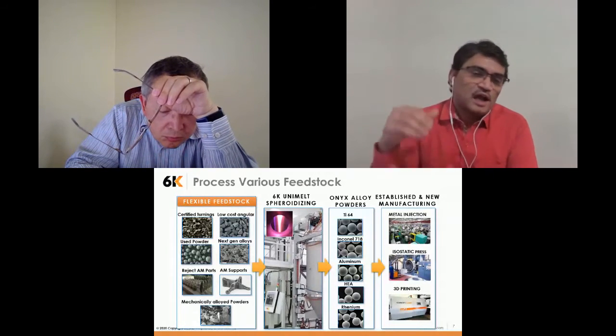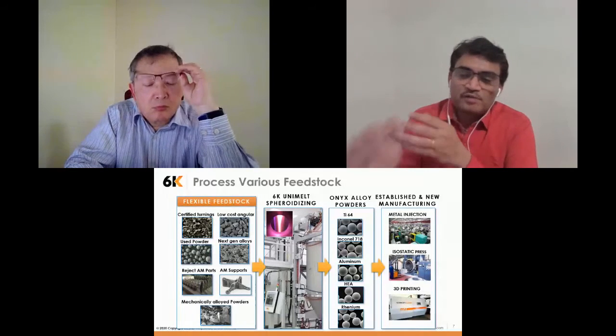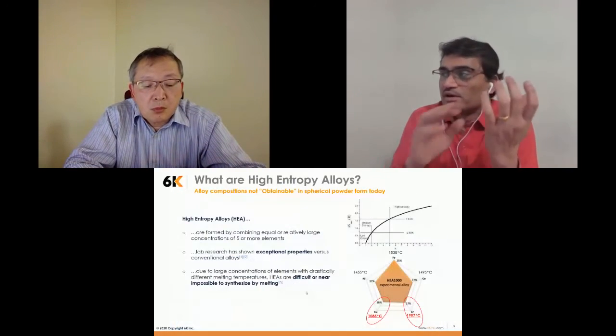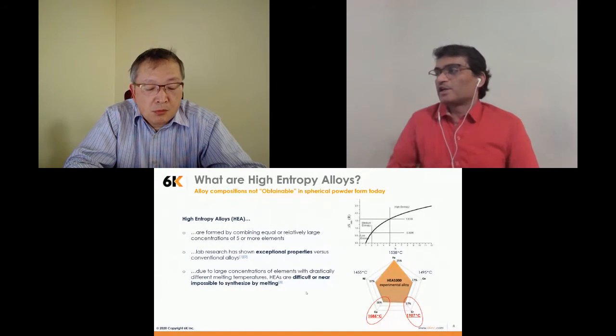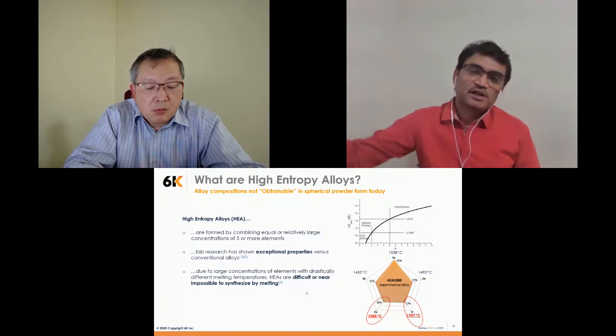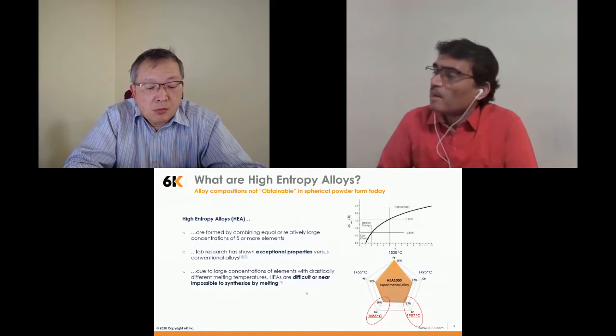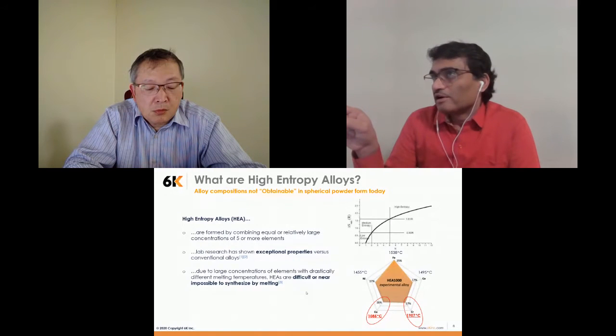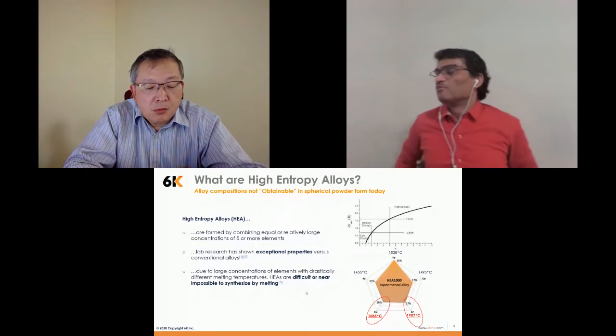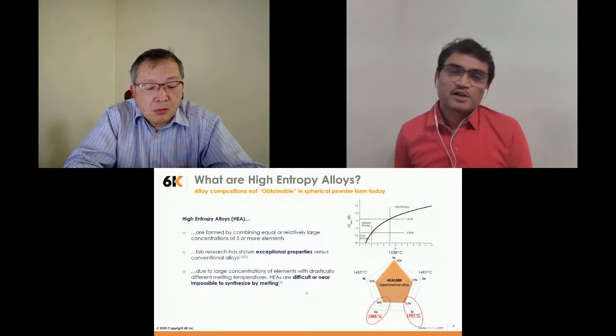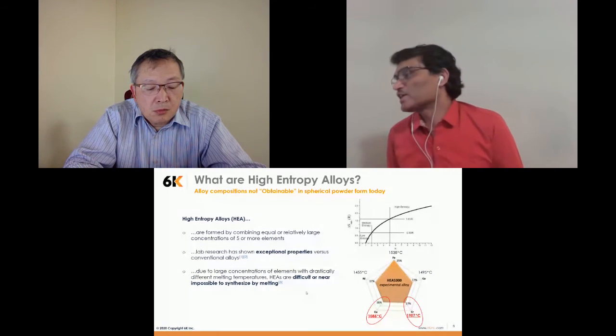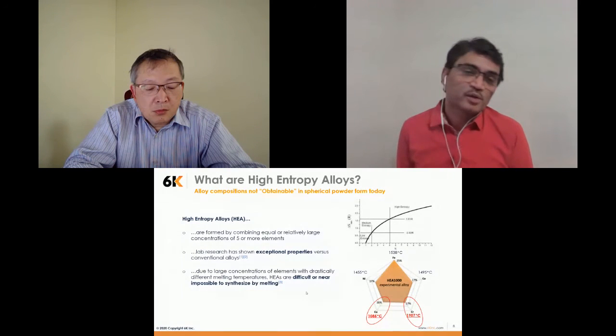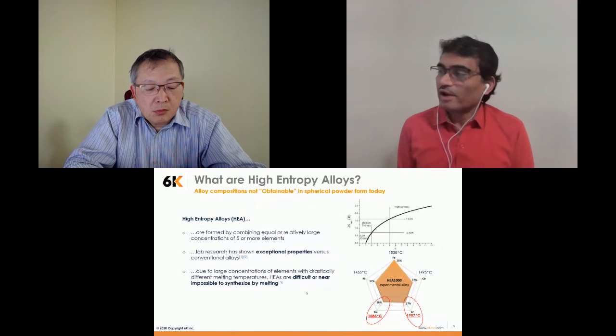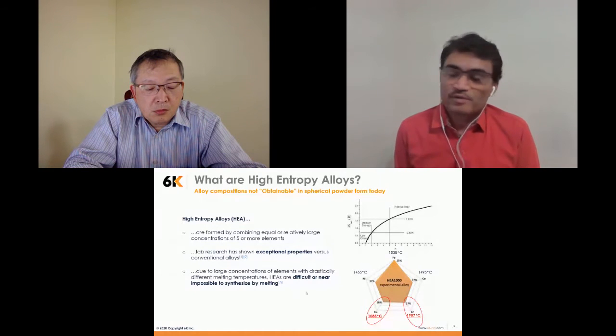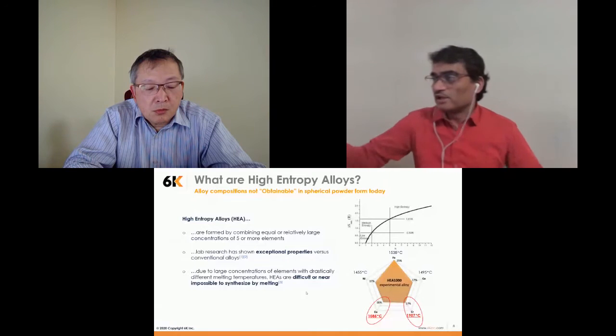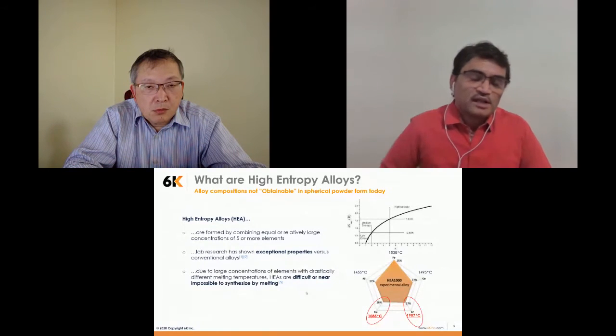So high entropy alloys are a different family of alloys, termed high entropy alloys. If you can see this little plot there, high entropy alloys are generally those which have entropy of mixing more than 1.6 R. And that corresponds to a minimum of 5 elements. On the x-axis, you can see the number of elements in equiatomic compositions in the alloy, and on the y-axis there is the entropy of mixing. So where there is an onset of the linear portion of that plot, that's termed as high entropy alloys.